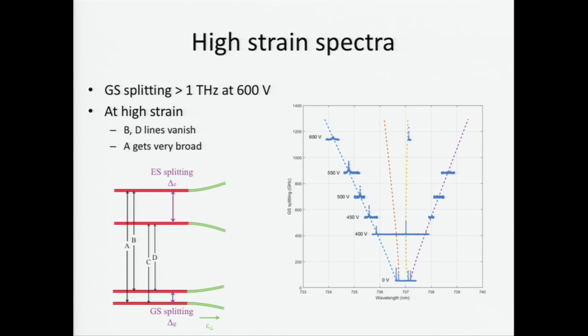So the amount of the shift in the transition frequency is much, much more than the inhomogeneous distribution. Inhomogeneous distribution means when you don't do anything, if you look at a different bunch of silicon vacancies, statistically it has some kind of standard deviation. That number is typically around, I think, 5, 10 gigahertz. And with our system, we can tune by at least an order of magnitude, actually much more, about 2 or 3 orders of magnitude more, like 100 or 1,000 gigahertz, such that if you have 2 emitters whose transition frequencies are far away, it's easy to bring them together into the same frequency.